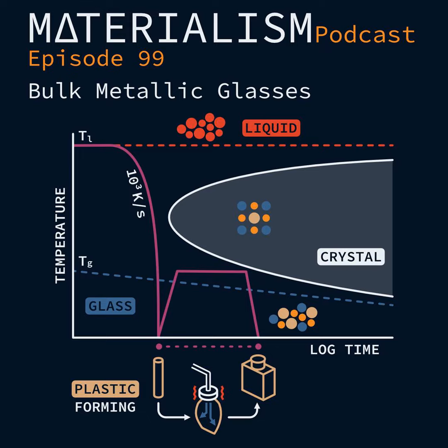Exactly. That was the main idea by Pol Duwez, who is often credited as the inventor or discoverer of metallic glasses. I can say a few words about this maybe, in a minute. I'd love to hear it. But that's exactly the idea. The time scale, if you take a pure element, is that they buzz around with a frequency of about 10 to the 13 hertz. And so all they need to do is collectively buzz and form something that looks like a crystal, and that leads to crystallization, overcoming the nucleation barrier.